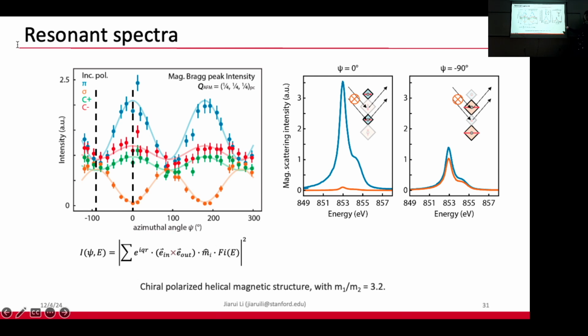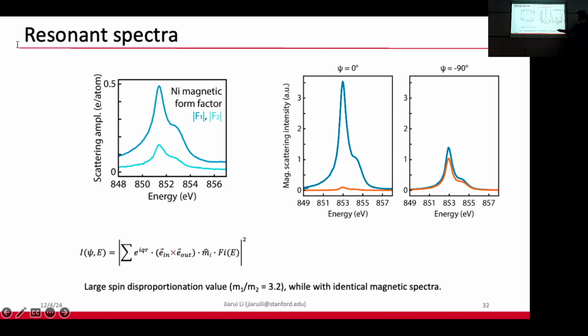And since we have this enhancement or suppression, we can measure this spin spectra for two different spin clusters. And by some mathematical treatment of these two measurements, we can obtain the nickel magnetic form factors as shown here. And this corresponds to their electronic structures as well as the magnetic moment sizes. So the magnitude or the height of this signal is proportional to the magnetic spin moment. And this is roughly 3 times larger in nickel 1 compared to nickel 2. So there's a factor of 3, consistent with what we have from the magnetic crystallographic measurement.